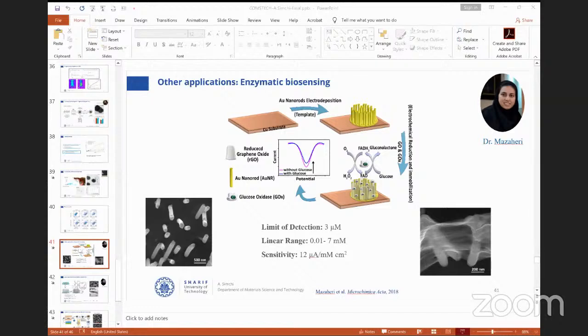Then we decided to incorporate graphene oxide nanosheets in between the gold nanorods. We found that the enzyme will functionally conjugate to the surface functional groups of graphene and graphene oxide, and then the gold nanorods transfer the electrons and make the detection very, very quick and very precise. She showed that the system works extremely well with high performance and quick, and we examined it even in the laboratory, and we tested it against the laboratory detection which we do usually every day.